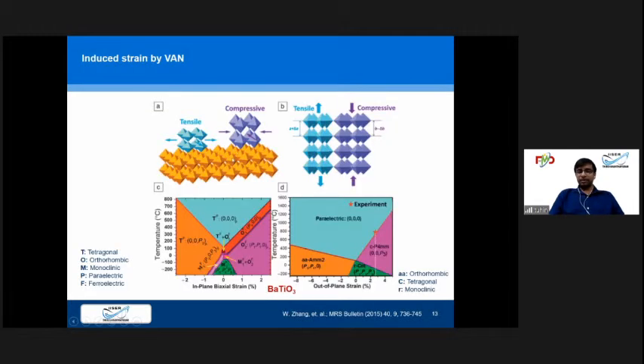If the substrate has a bigger lattice constant, then it tries to compress the material it is depositing. So it's called compressive strain. And if it has a smaller lattice constant than the material we want to deposit, it gives a tensile strain. Now, between the matrix and the column, there also needs to be a crystal match. If they have a difference in lattice parameter, then we can also create tensile and compressive lattice strain depending on the lattice match between these two different materials.